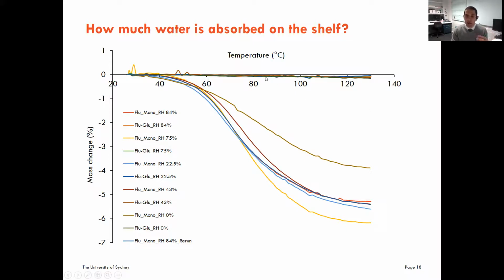Now, I realize that these colors are a bit overlapped here, but I can safely and happily say that all these colors here were our co-crystal samples, showing almost 0% weight change or mass change. All of these other ones were the monohydrate at differing levels of relative humidity. Obviously, they've absorbed different amounts. What does this mean in terms of application? This means that our co-crystal, reaffirming our theoretical results, really is going to be a much more stable product in terms of relative humidity. So we looked at that humidity transformation from the anhydrous form 2 to the monohydrate.